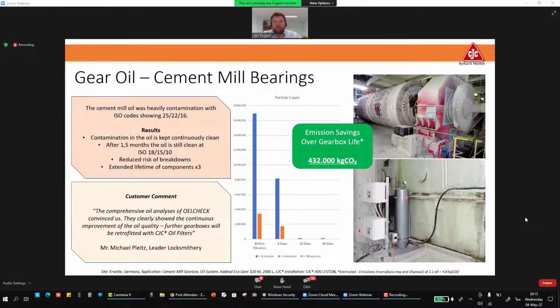To give you another example, here is a cement mill bearing system, very contaminated. The oil was cleaned out, and in about a month and a half the oil was still very clean and kept clean. As you can see in the graphs, before filtration there were an awful lot of small particles, and you reduce it down to basically nothing, and your lifetime is so much longer on all your components: bearings, gearboxes, pumps, valves, whatever you could have here. And emission savings just on this one alone was 432,000.